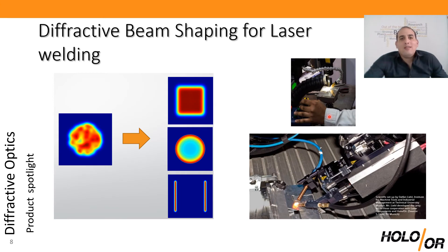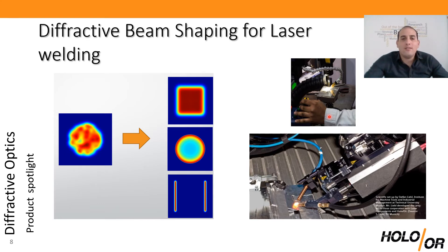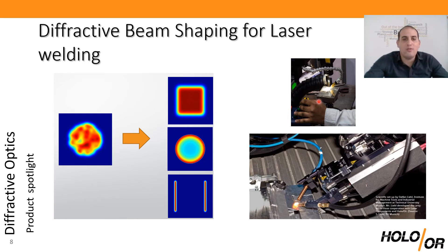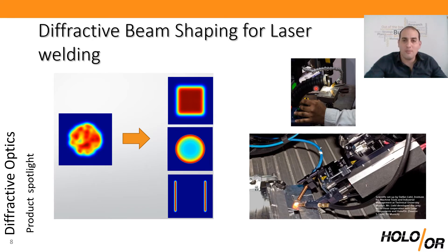Why do you need laser beam shaping in welding? It has been shown in multiple articles and in past projects we were part of, like the Taylor Weld European project, that using a tailored intensity distribution has multiple process benefits. For example, a ring-type mode with a central spot can increase throughput without spatter, improve the weld angle, improve weld quality and hardness, and reduce inclusions — all achievable by shaping the laser spot.